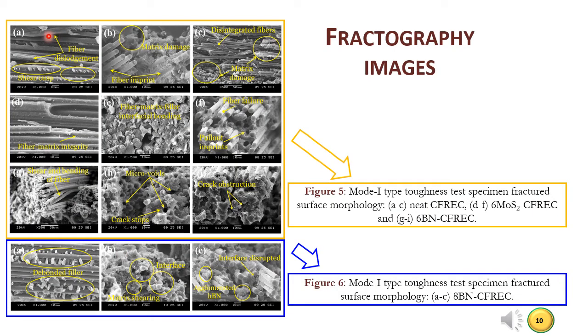This shows fracture morphology of various composites in mode 1 toughness test. Cracks developed in the matrix propagate, leading to fiber dislodgement. Shear cups represent brittle failure of neat composite. Multiple cracks dislodged matrix around fibers. Due to this, fiber disintegrates from matrix. This evidence supports the lowest KIC of neat CFREC. 6 MoS2 CFREC reveals improved fiber matrix filler interfacial bonding compared to neat CFREC. Carbon fiber failure demands more energy to fracture. Fracture morphology of 6BN CFREC depicts shear and bending of carbon fiber. hBN particles in the epoxy matrix cause obstruction to crack propagation.